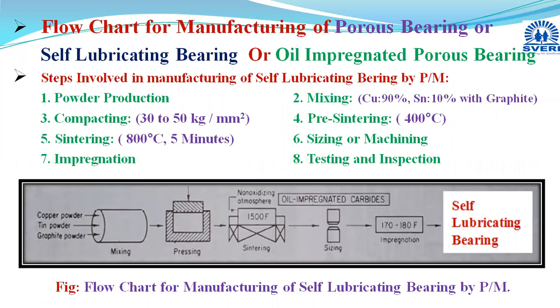Sufficient pressure is applied so that a proper bond is created between the powder particles in this pressing stage. The generally used pressure for manufacturing a self-lubricating bearing is 30 to 50 kg per mm square. Within this range, you have to use the pressure. If the pressure values are lesser than this, the product obtained at the end of that compacting stage will be very fragile.